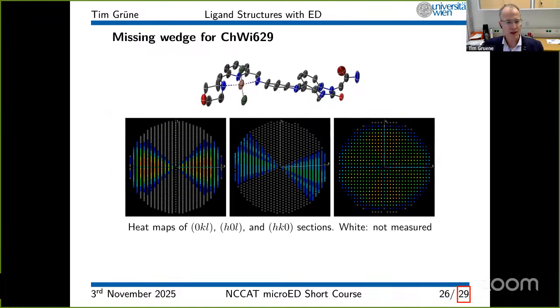A technical problem that we have with electron diffraction is illustrated here. You see the molecule itself has got a very flat shape, and this is also reflected by the shape of the crystals. If you remember, they were really, really flat species. And in one direction, the data are really complete. So everything that is colored in this HKL plot, in the HK section, we have nearly complete data. But when we rotate it by 90 degrees in either direction, we have a huge missing wedge. And that's a common problem in electron diffraction, that because we cannot rotate the holder by 360 degrees, because the grid is then covering the beam, we cannot collect complete data from a single crystal.